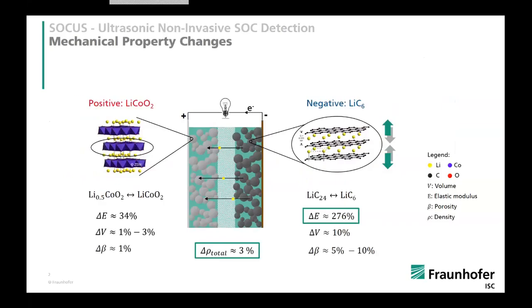So, of course, you all know this picture, and you know about the properties of what happens in a battery cell electrochemically wise on the anode and the cathode. And it's also very known that during charging and discharging, or lithium intercalation and deintercalation, also the mechanical properties change quite a lot. For the positive electrode here, quite an old-fashioned lithium cobalt oxide electrode, effects are not so massive. The elastic modulus changes only by approximately 30%, where the volume and the porosity are nearly unaltered. On the negative electrode, however, there's a tremendous increase of elastic modulus, nearly threefold compared to the non-intercalated state.